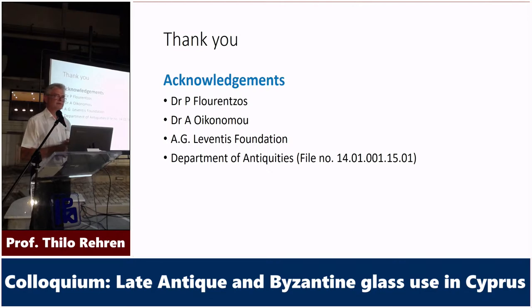Now, if you do that and then you recycle that broken vessel and you have a dot of blue glass on it, which has a tenth of a percent of copper oxide, that doesn't sound like much, but expressed in parts per million, that would be 1,000 parts per million of copper oxide. And if you have only 1% of that glass in your recycled glass, you still have 10 ppm copper in the whole lot, and you can analyze for that concentration. So that copper, lead comes with it, tin sometimes comes with it. With a proper analysis, laser ablation, ICP-MS, you can see that it's exactly one of those recycling indicators that we are chasing.